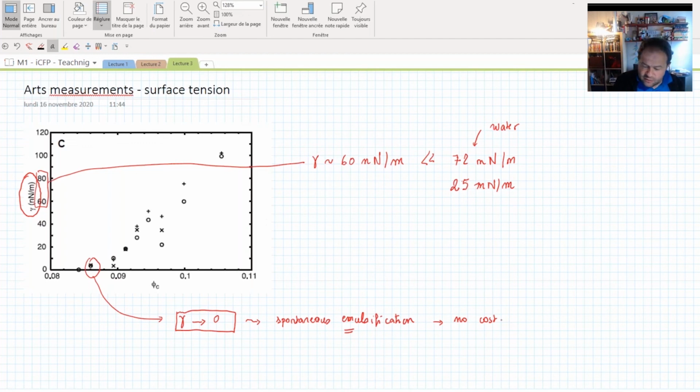The only thing that I have to say is that these experiments usually are not easy, because you have something that will kill any of your measurements, and you have to take care when dealing with this kind of measurement. It is that you have to deal with the vibration. Because of course, if you have vibration on your sample, you will have waves which are unrelated to the waves excited by the temperature.